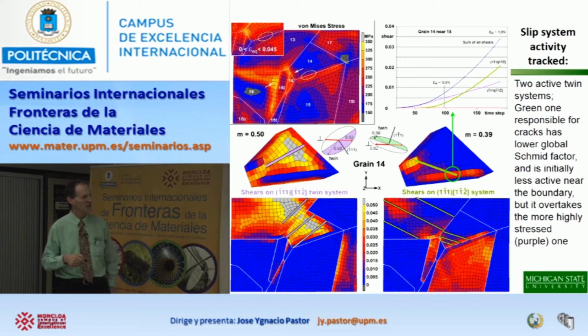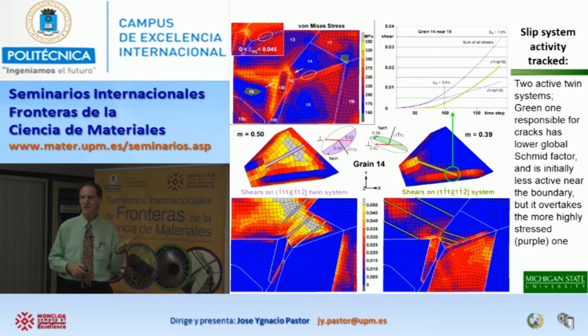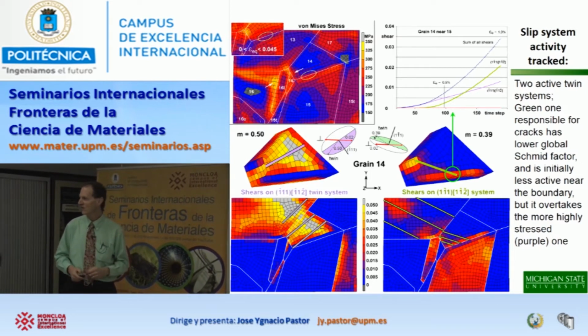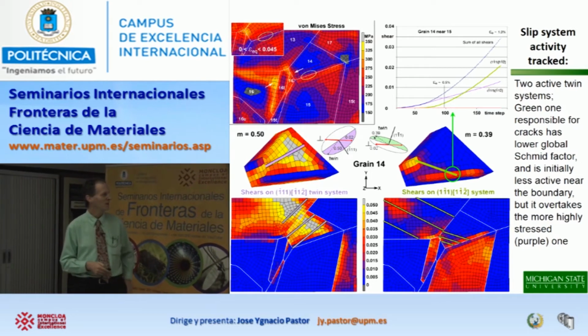But if we just look in this neighborhood where the cracks actually developed, it turns out, if I just focus here, that in the beginning, this twin system was more active, and later on, this one took over and ended up straining more. So if we look very locally in a simulation, we could see that we have conditions that would account for what we saw experimentally. So this gave us the sense that we could begin to model very subtle features that help us predict the beginning of cracking.